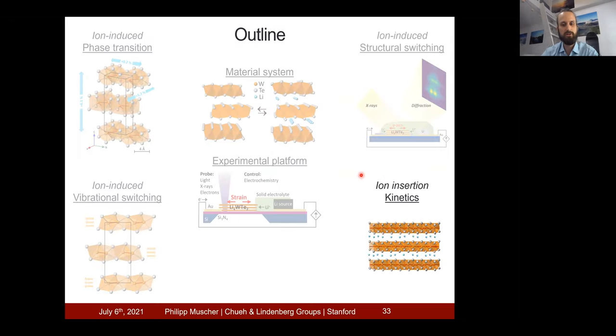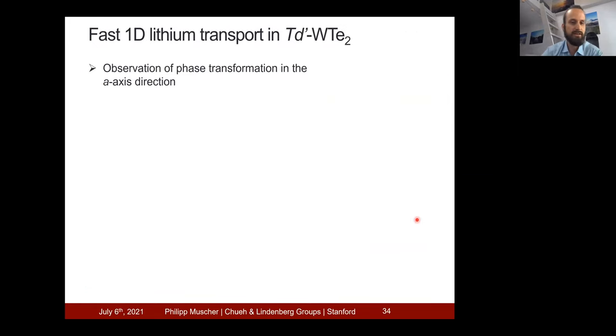Now I'd like to turn to the final section of my talk, which is on the ion insertion kinetics. This is really important because only if the ion insertion kinetics are fast enough can we actually use all these changes for dynamical switching, because only then can we switch the material fast enough. I suspected fast transport along the a in-plane axis of tungsten ditelluride, because if you remember the optical video from the beginning, the phase transition was occurring in the direction of the a axis of the crystal.